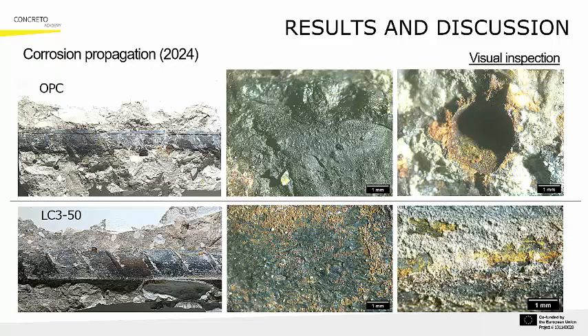Corrosion propagation was first examined through visual inspection of the rebars after extraction of the 2024 cores. These images taken with an optical microscope reveal a remarkable contrast between the two concrete systems. While the rebar from OPC concrete shows extensive corrosion products and an almost 3 mm pit, the LC3 concrete rebar shows only corrosion products that appear to be superficial, with no evidence of deep pitting.